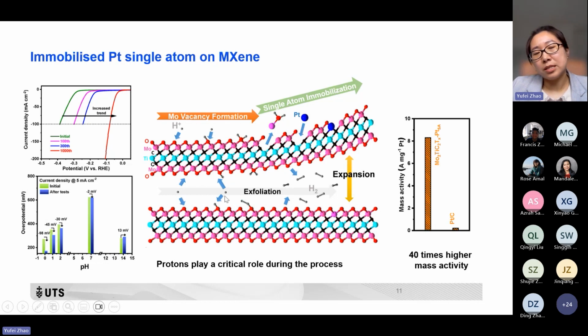And the continuous generation of hydrogen during this HER process will make the MXene exfoliate from the loosely packed structure to form these exfoliated two-dimensional nanosheets. And also the interaction between the hydrogen and oxygen may form the OH2 structure. This structure may drag the molybdenum out from the structure to form the molybdenum vacancy, and the platinum ions can be captured by the vacancy to form this kind of single atom catalyst.